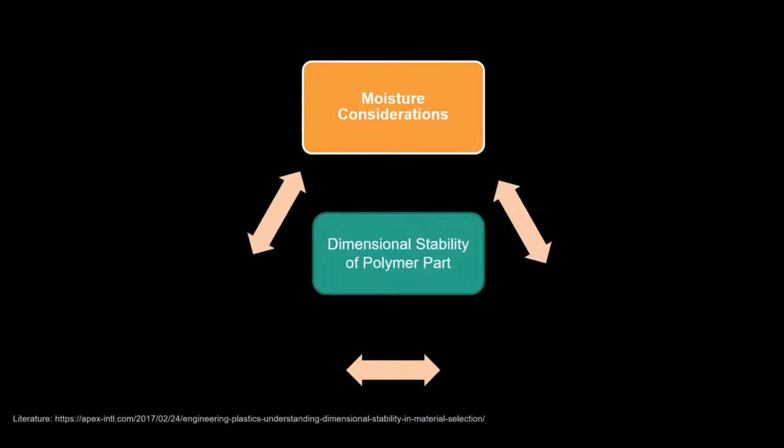For example, an aliphatic polyamide such as PA66 was specified for an application with tight tolerances. However, due to the moisture uptake during the use phase, the part performance decreased and a replacement material is needed. In such a case, a semi-aromatic polyamide, a PPA, can be an alternative since it has the lowest moisture uptake of all polyamides. There are also other polymers such as a polyetherimide, a PPS or a polyether ketone, which have excellent mechanical and also moisture performance.